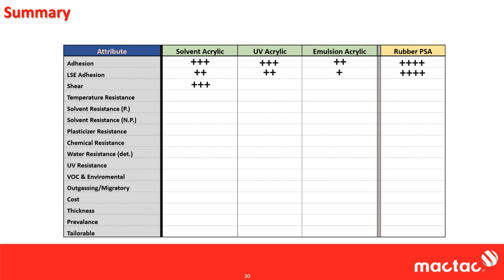In terms of shear, you get pretty good shear. Again, comparable shear out of the two, UV and solvent. Emulsion acrylic, you're going to get 1. Again, this is starting to improve, but you don't get really high shear out of emulsions because you don't get a lot of interaction between the polymer chains. Rubber, you get a lot of interaction there, so that's a 4.